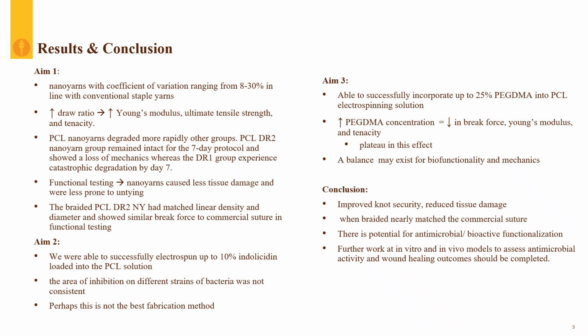However, our nanoyarn with a draw ratio 2 remained intact for the 7-day protocol and did show mass loss and correlated loss in mechanics, whereas the DR1 group had catastrophic degradation. Functional testing showed that the nanoyarns caused less tissue damage and were less prone to untying. And then we even braided our PCL nanoyarn group, and this showed to have matched linear density and diameter to the commercial suture and showed similar break force as well. So we're right in the ballpark of a commercial suture here.